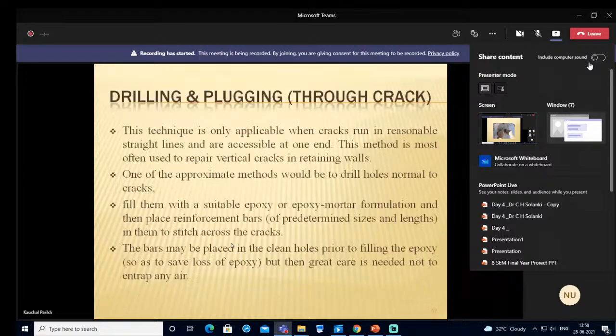Another repair method is nothing but drilling and plugging through cracks. This technique is only applicable when cracks run in semi straight lines and are accessible at one end. This method is mostly used for repairing vertical cracks in retaining walls. One of the appropriate methods is to drill holes normal to the crack, fill them with a suitable epoxy or epoxy mortar formulation, and then place reinforcement bars of the predetermined size and length to stitch across the cracks. Here the bars will be placed in the holes prior to filling the epoxy, but great care is needed not to trap any air so that the repair can be carried out effectively.